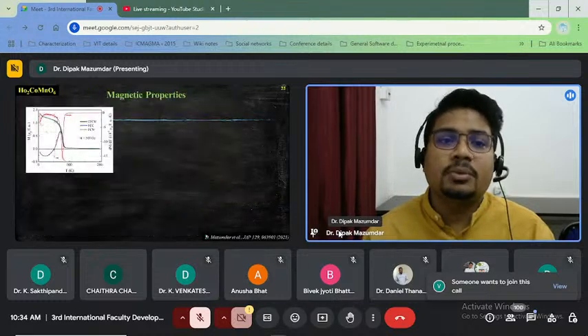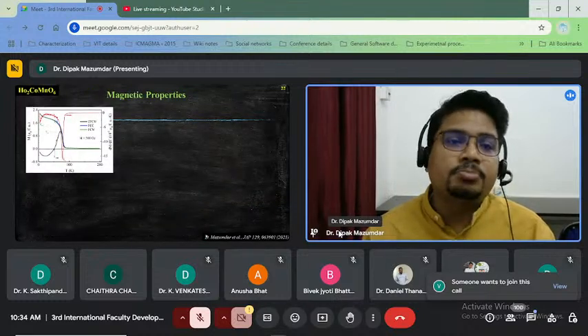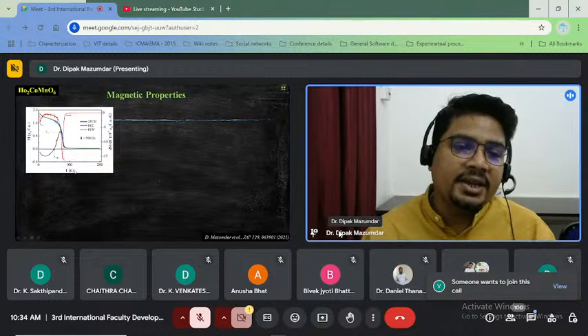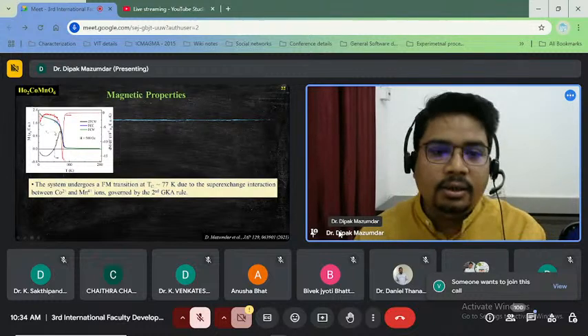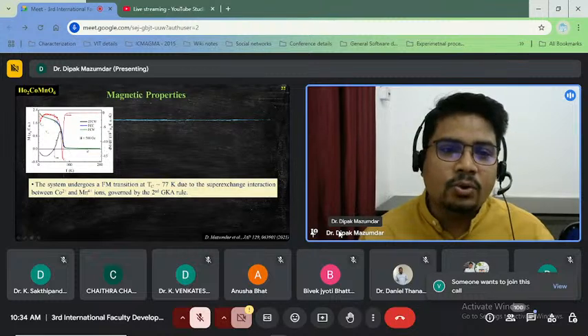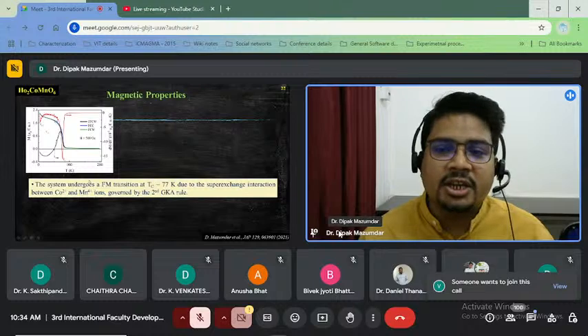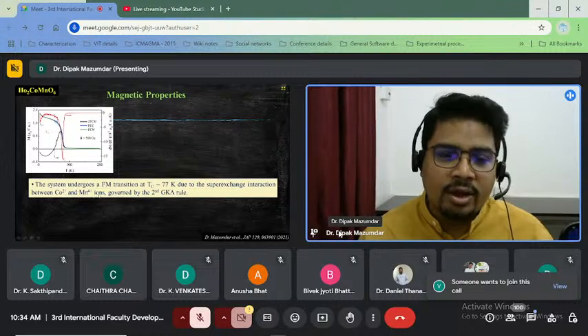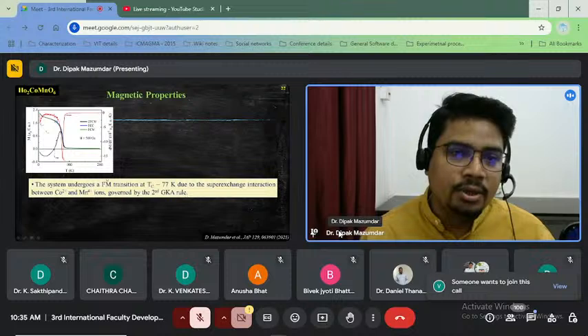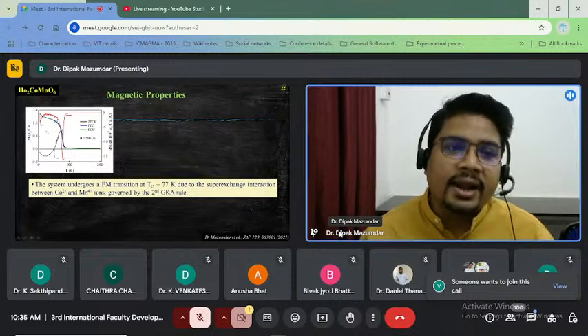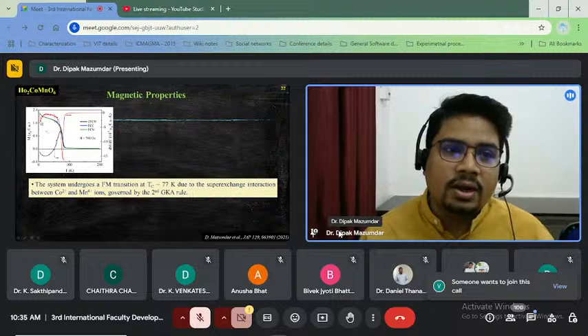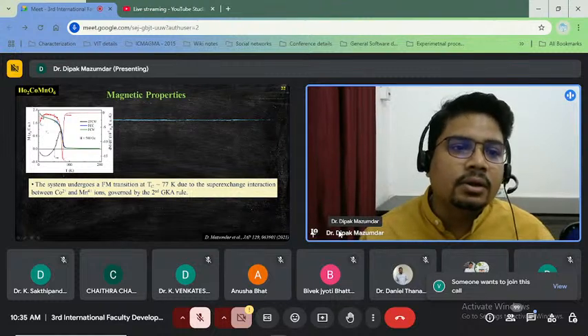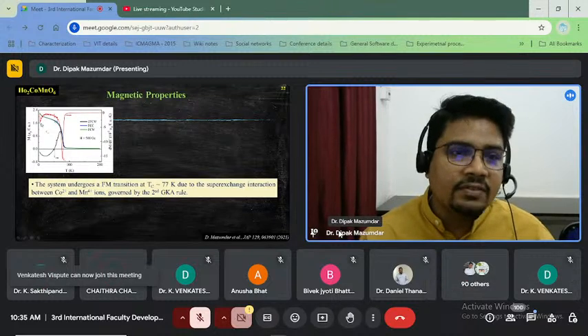Next, I will discuss the magnetic properties. This is the temperature dependence of magnetization data, and it shows that the system undergoes a ferromagnetic transition around 77 Kelvin due to the superexchange interaction between Co2+ and Mn4+ ions, governed by the Goodenough-Kanamori rule. In this region there is no effect of the rare earth ions. The rare earth ions start ordering after around 10 Kelvin, antiferromagnetically.